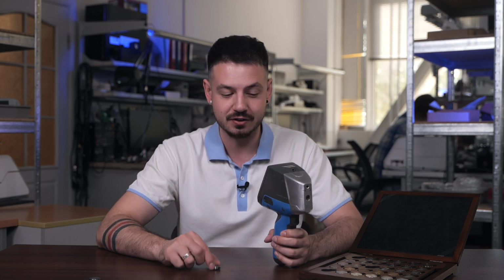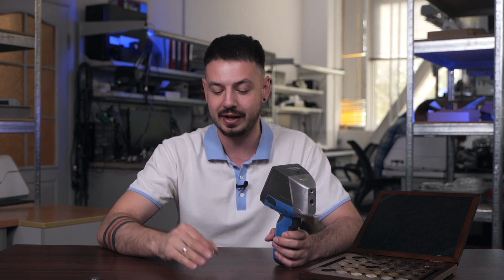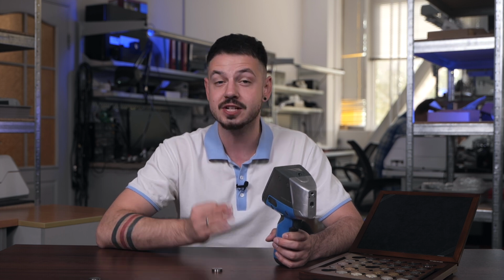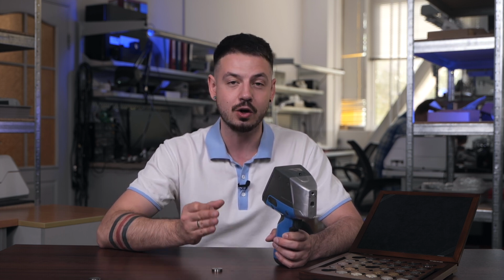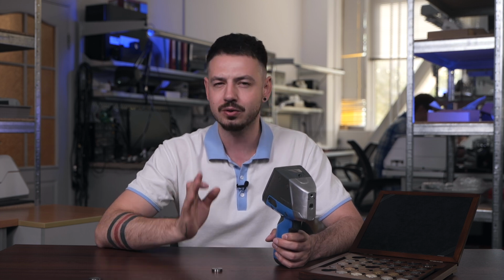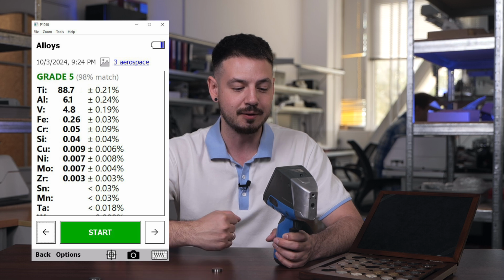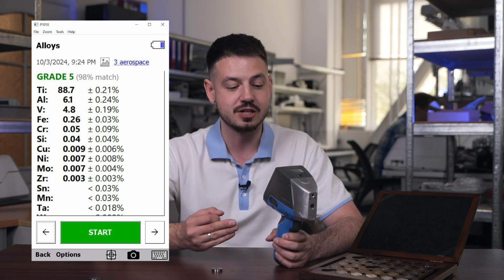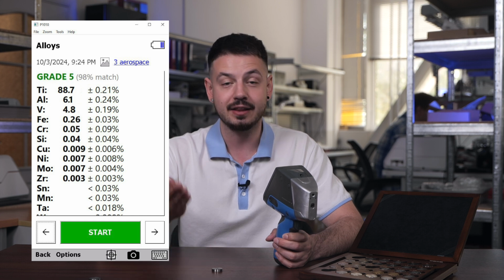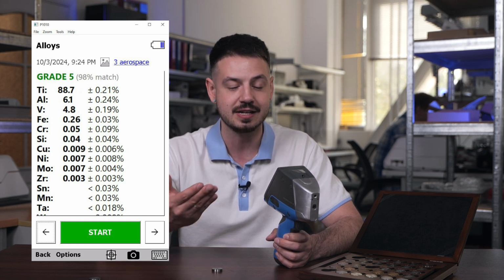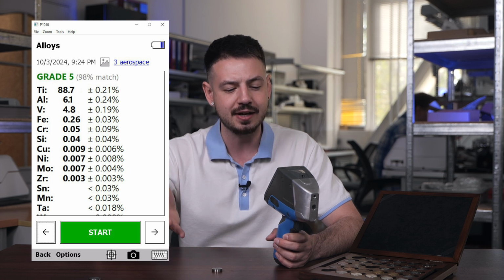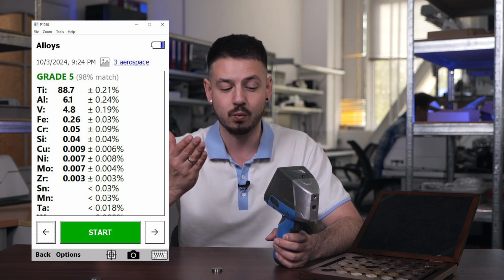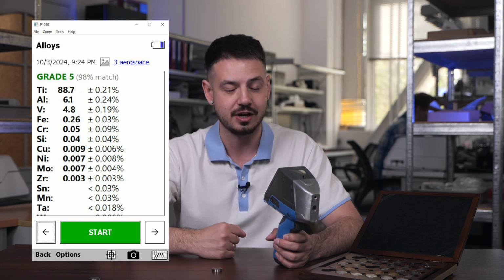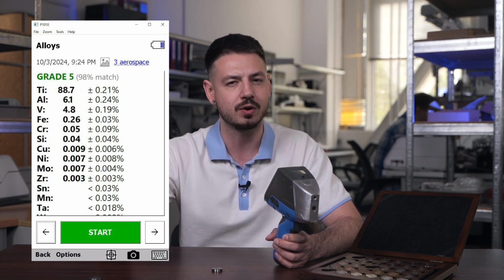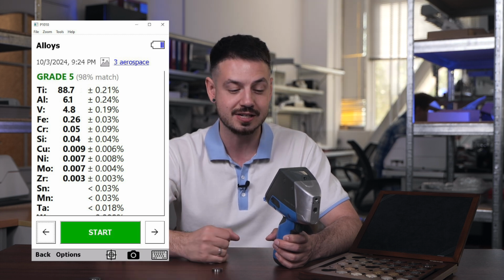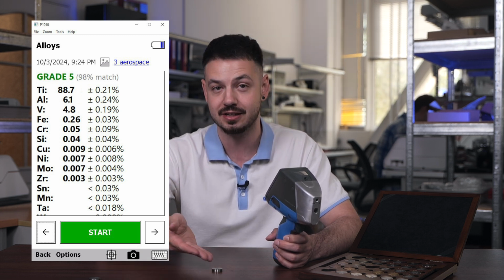Alright, so we finally have the results of our third and last sample for today, and looking at the data we received in just 5 seconds, we can say that it's really close to the average data for this alloy. So let's take a closer look. The leading element, as expected, is titanium in a concentration of 88.7, and the average concentration for this element is 88.5, with an appropriate error of 0.4. So we absolutely fit in this range, and if you set more time, like 15 or 20 seconds, you will definitely receive the right proportion of this element in this sample.